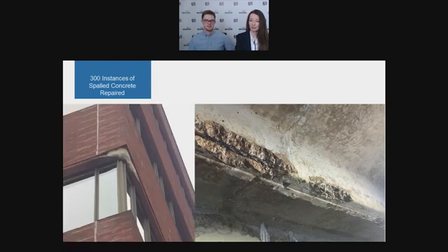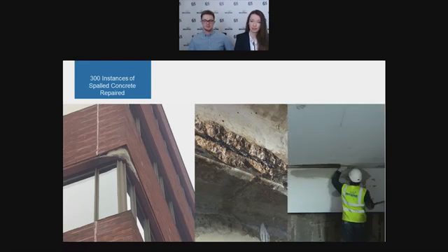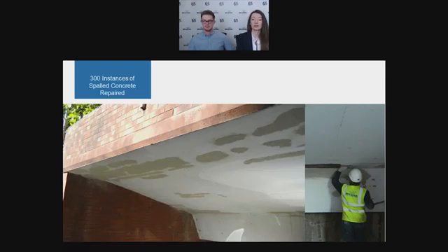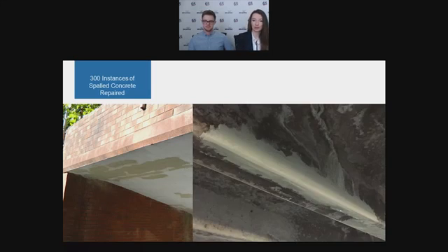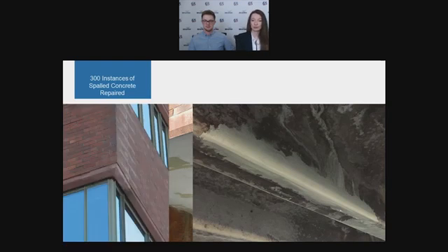So at this office, literal chunks of concrete were falling down from the facade, which is obviously a massive health and safety risk. A full repair was necessary, which Belzona was able to provide with just the one product, Belzona 4141. In total, over 300 vertical and overhead repairs took place around the building over about 3 months of working weekends only, which is quite fast considering. And then the office was completely restored, with minimal disruption to its everyday operation. A final reason Belzona 4141 was chosen was because it can be tinted. So in this instance, the red tint ensured the system blended into the office's facade, and these repairs were barely even visible.